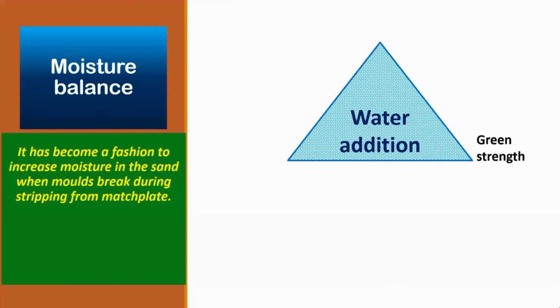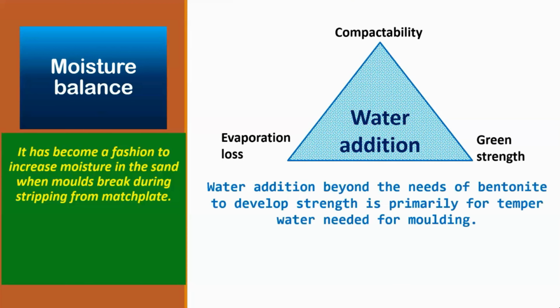But basically the moisture is required for activating the bentonite and produce green strength in the sand. And the second aspect is about compactability. And the third is, as you mix the sand and then produce this compactability, by the time you reach the molding machine, there is going to be evaporation loss. So you add some more water to compensate for this evaporation loss also. So water addition beyond the needs of bentonite to develop the strength is primarily for temper water needed for molding.